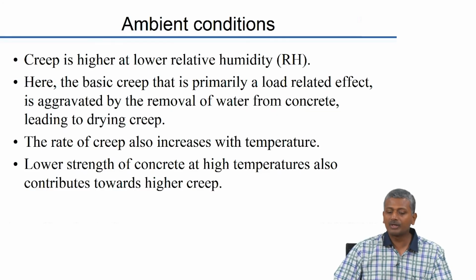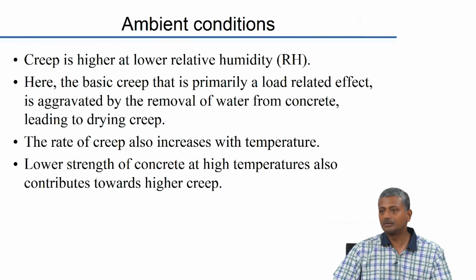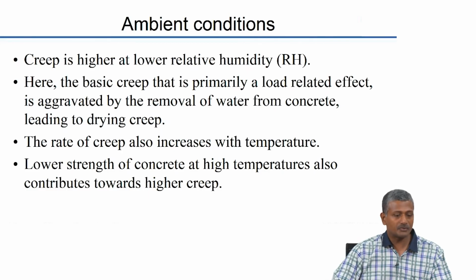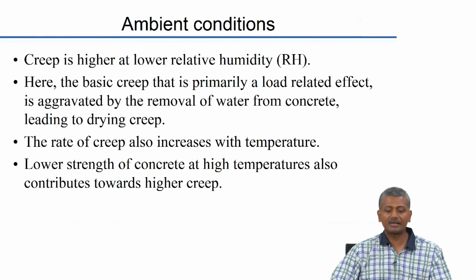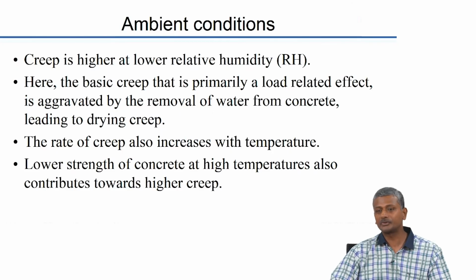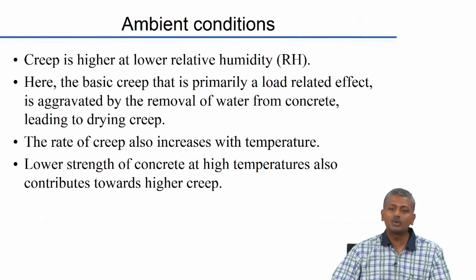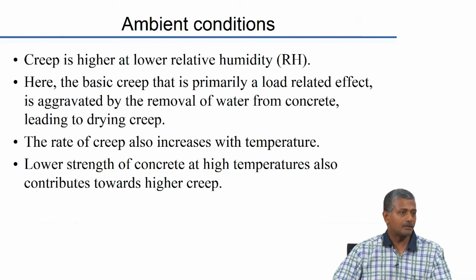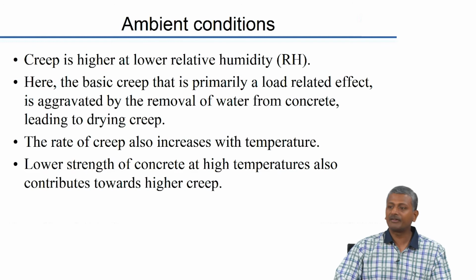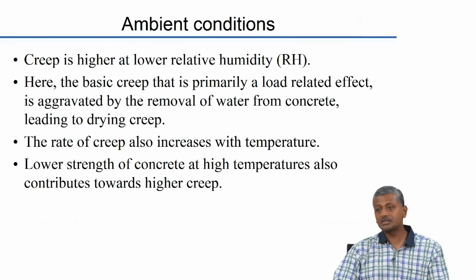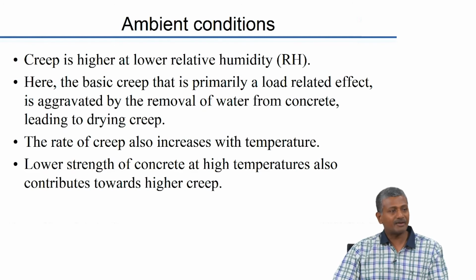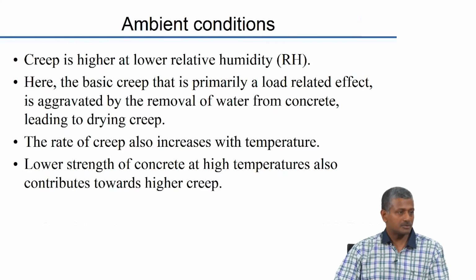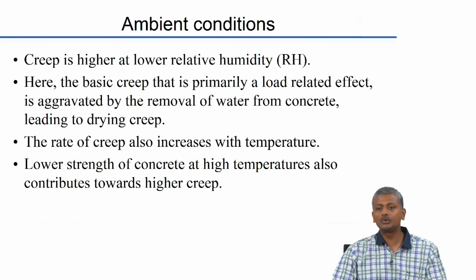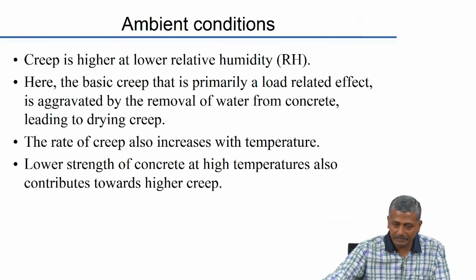Okay. The rate of creep also increases with temperature. The higher the temperature, the higher the rate at which creep will happen, and lower strength of concrete at high temperatures also contributes to greater creep. So, there are a lot of factors that work together in unison to change the behavior of concrete in the long term. It is not just the temperature, but a combined effect of the strength which is lowered at high temperatures and the fact that temperature increases the rate of strain during creep. Okay. So, all these factors together will lead to an overall increase in the creep capacity.